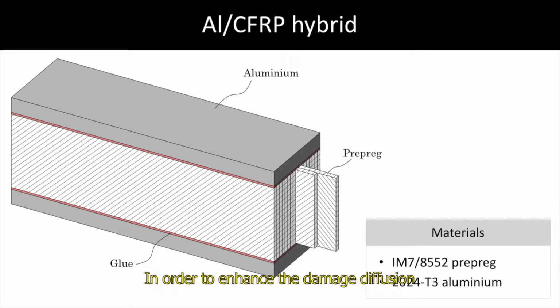In order to enhance the damage diffusion of the microstructure, a new type of hybrid microstructure was conceived. The inner and outer layers of the cross-lamellar CFRP were replaced with aluminium. The microstructure was prototyped based on the bonding procedure with IM7/8552 prepreg and 0.4 mm thick 2024 T3 aluminium.